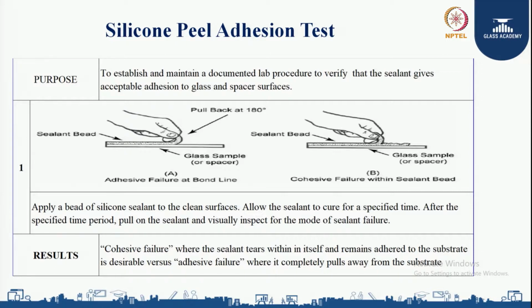As shown in the figure, when pulling back at 180 degrees, the glass sample separates from the spacer, which is an adhesive failure. In figure B, there is a cohesive failure, where the sealant tears within itself. An adhesive failure is a bad sign, whereas a cohesive failure is recommended. So a cohesive failure, where the sealant tears within itself and remains adhered to the substrate, is desirable, versus an adhesive failure where it completely pulls away from the substrate.